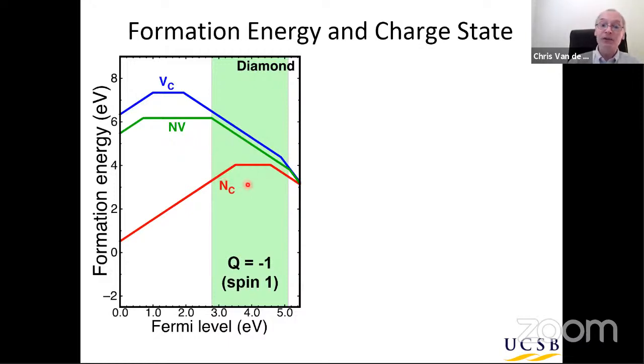And it turns out if nitrogen is the dominant impurity, then the Fermi level will be determined by this dominant impurity. How is the Fermi level determined? It's basically determined by charge neutrality, okay? Overall, macroscopically, our material needs to be neutral. If you put a large concentration of nitrogen in the material, larger than any other defect or impurity, then the Fermi level position is going to be determined by this nitrogen substitutional impurity, which could be positively charged or be neutral, or it could be negatively charged.